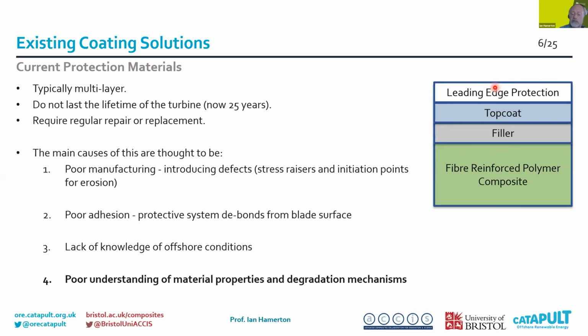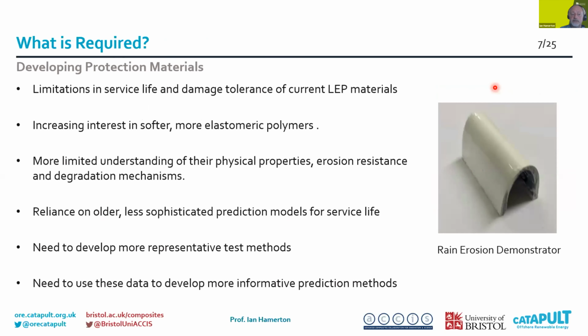And so this is about understanding the material properties, improving the test facility, because the move generally has been away from metallics through harder polymers and increasingly softer, more elastomeric materials. So these are structures which will be a little bit more rubbery in their appearance. So you might see typically polyurethane, cross-linked polyurethanes at the surface. This example here shows you a typical rain erosion demonstrator mimicking the leading edge of a blade.